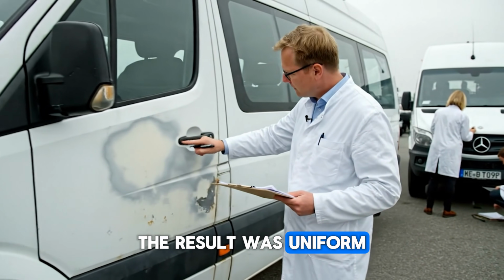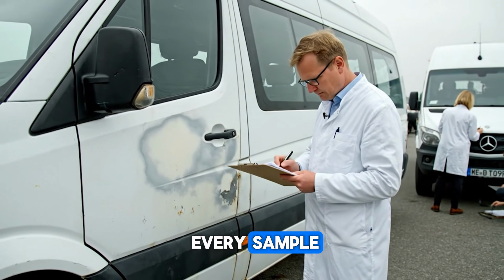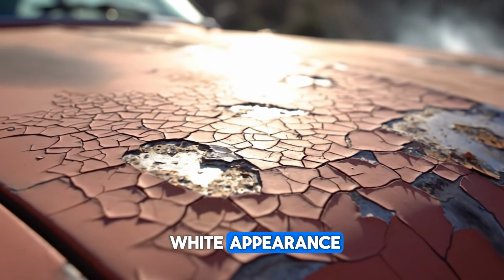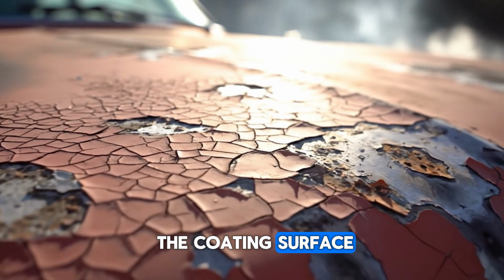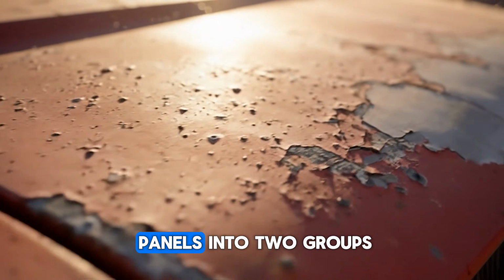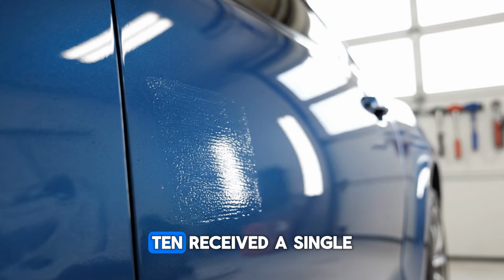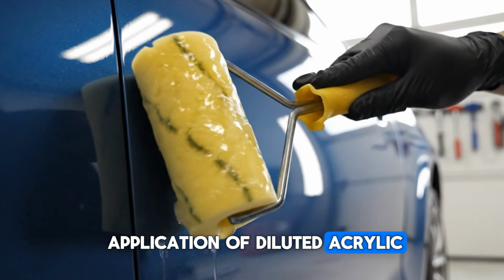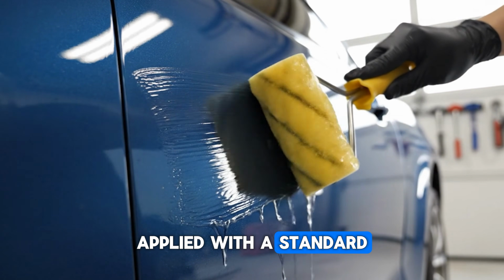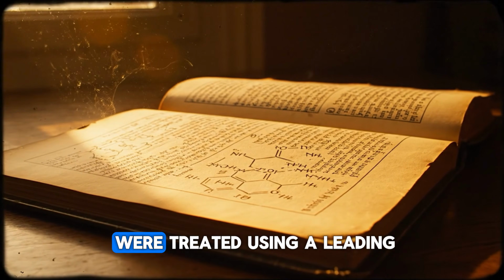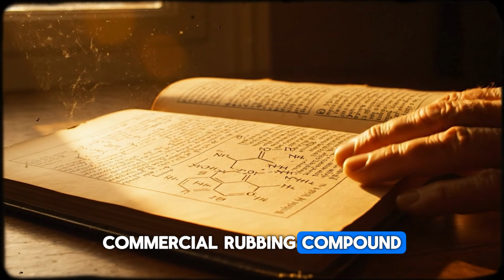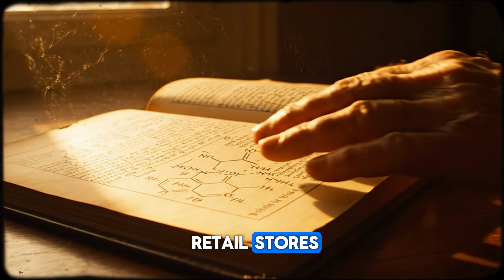The result was uniform stage 3 oxidation across every sample, characterized by a chalk-white appearance and widespread microfracturing of the coating surface. The experiment divided the panels into 2 groups. 10 received a single application of diluted acrylic copolymer resin applied with a standard foam pad, while the remaining 10 were treated using a leading commercial rubbing compound widely available in automotive retail stores.